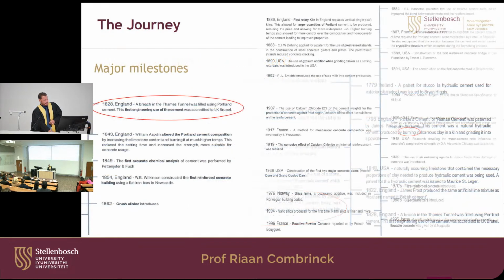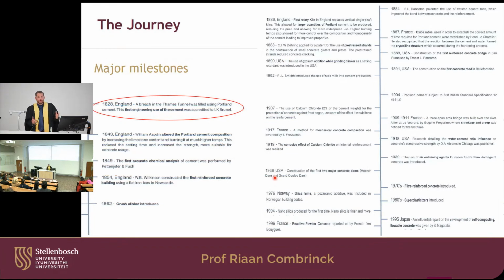Then some milestones in the journey of concrete. The first one I would say is the first engineering use of cement to fix the Thames Tunnel with Portland cement. And this was actually the first breakthrough. You can see that this is an engineering material that you can use to great benefit. Then in 1854, they used it with steel. So this was the first time you could use concrete in a tensile environment as well by introducing reinforcing steel. And that was also a big breakthrough, because now you could start spanning large areas where normally you needed a dome structure like the Pantheon.